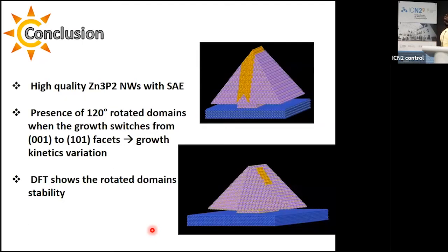Concluding, with selected area epitaxy, it's possible to grow high-quality zinc phosphide nanowires. And these nanowires present 120-degree rotated domains, depending on the facets of the seed at the early stage, that are due to growth kinetic variations. And these domains we demonstrated with DFT simulation that are stable from electronic point of view and from the structure point of view.